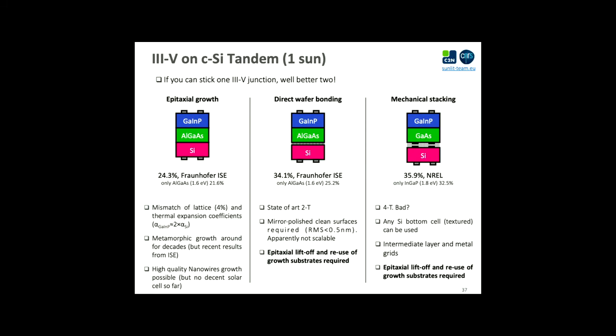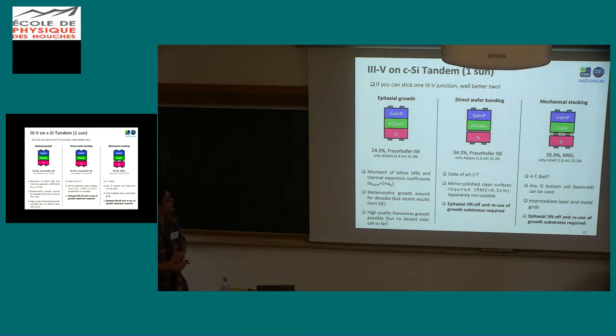The other two approaches are direct bonding and mechanical stacking. So the idea here is that you first start to grow your top cell. In this case, they use 2 cells, why not? On the gallium arsenide wafer, you remove it from the gallium arsenide wafer and you bond it on the silicon. And this bond is made basically by activating the 2 surfaces of the 2 wafers in vacuum and then putting them together. So this approach allows you to make a 2-terminal tandem. Best efficiency now is 34% by Fraunhofer ISE.